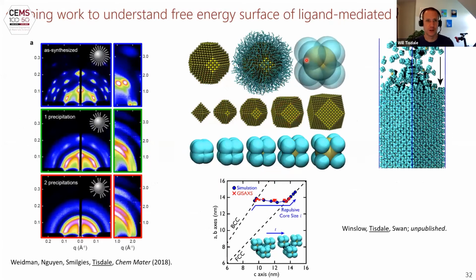We are doing ongoing work to try and understand the role of free ligand in mediating self-assembly. We know that the surface ligands are essential to getting ordered superlattices. If you strip off too many ligands, you don't get ordered structures. So soft materials interactions are at the core here. Sam has developed some coarse-grained models that can reproduce most of the observations, but those are still under analysis and unpublished at this point.